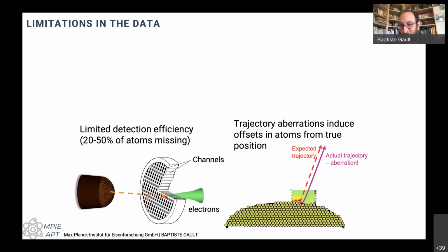The thing is, with these glass tubes that you see, we can't have 100% of the surface active. We always have a certain amount of the surface that corresponds to the junction between all of these tubes. So, depending on the geometry of the detector and the generation of microchannel plates that we use, we are going to lose between maybe 10% and 50% of the ions. But this is random. It just depends on where they land on the detector. It doesn't depend on their mass or their acceleration energy. So normally, if all goes well, we don't have species-specific losses like you could get from TEM, for example, because the low atomic number species are much harder to detect.